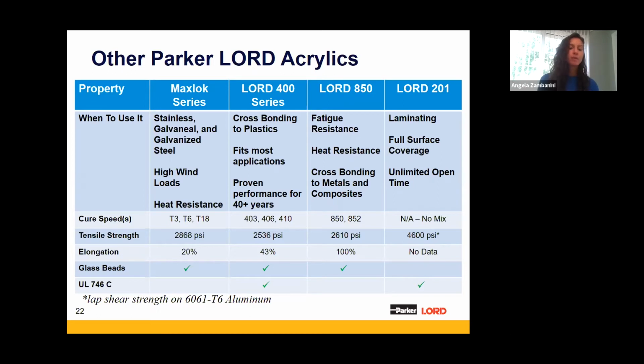This is different from the other 3 adhesives that I just mentioned because it's our no mix solution. What I mean by no mix is that you apply the adhesive on one substrate and then you take the other part, the accelerator, and apply it to the other substrate. And then you can trowel this, you can get full surface coverage, which is why some customers like this, but then you also have unlimited open time. So the adhesive won't start curing until you put the 2 materials together and they touch, and that's what starts a chemical reaction. So those are the 4 different products there.